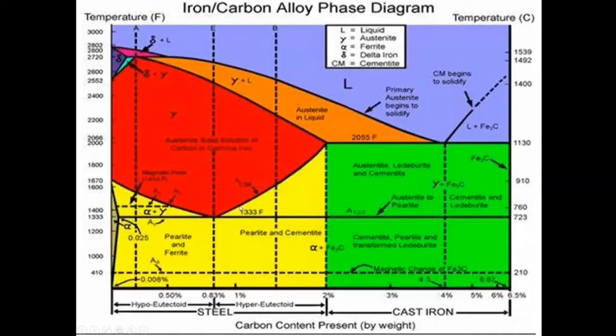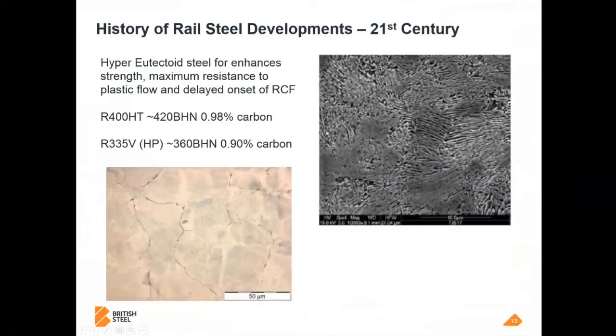grain boundary cementite. But you can see when etched in nital or viewed under your SEM, it's not really resolvable. But actually, if you etch it in sodium picrate at maybe 80 degrees, you can actually resolve this. You see it's thin, but it is very much there. The other thing to say is they only really heat treat the head. So the web and the foot of the steel have very, very coarse, continuous networks of grain boundary cementite. And it's not the way we choose to do it.